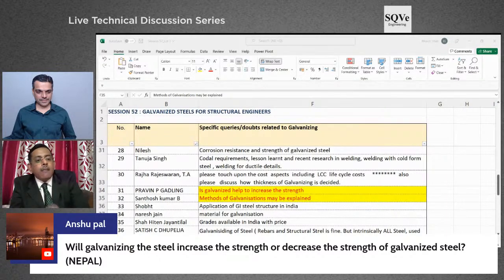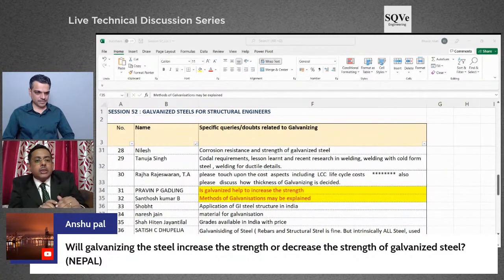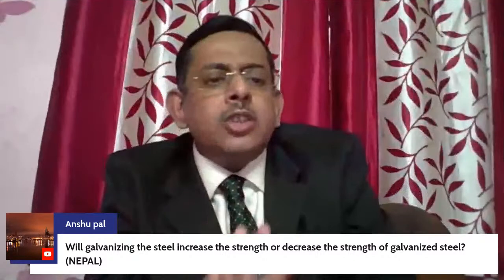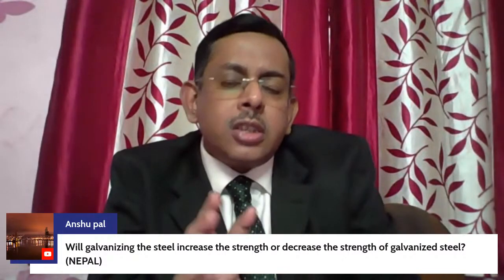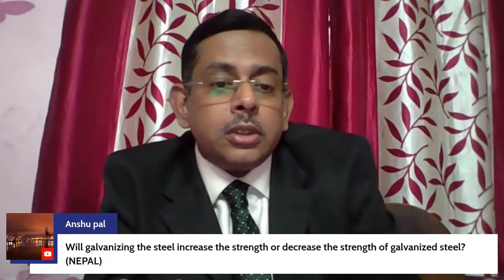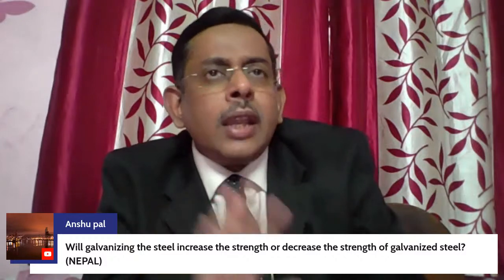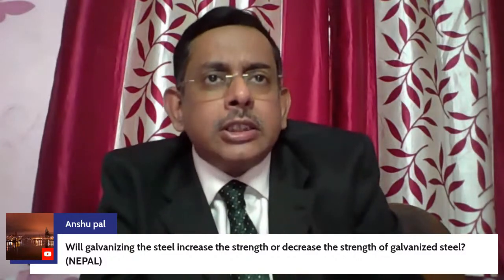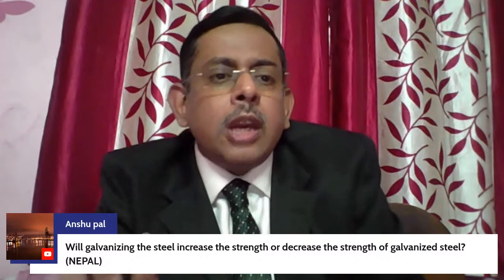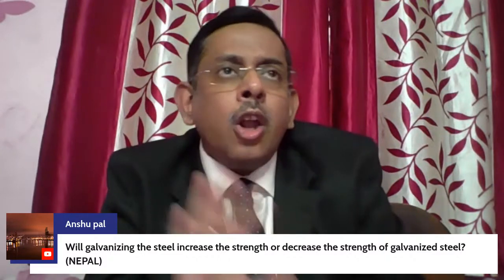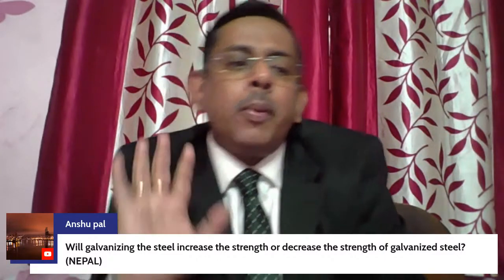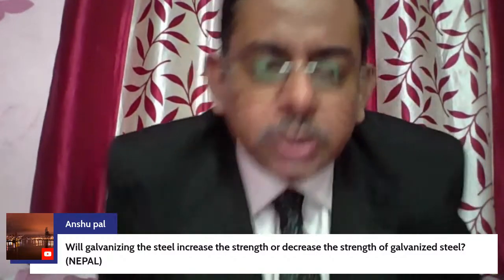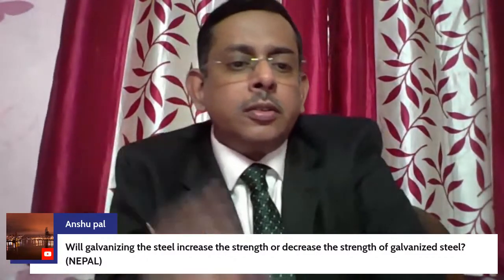It does not have any role in the microstructure because hot dipping is a surface phenomenon and it is done at 460. And at 460, for a few minutes, there is no change observed in the steel metallurgy or steel microstructures. So I can tell you, galvanizing does not have any role in determining the strength of the material or changing the properties of the material. Galvanizing is a coating process to give you better corrosion protection.